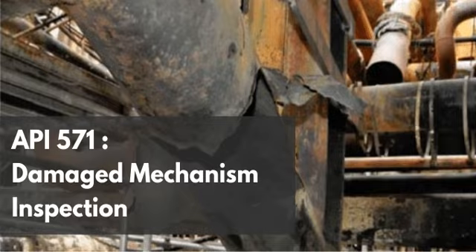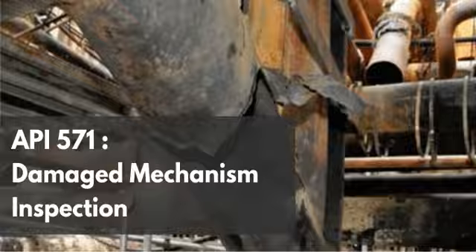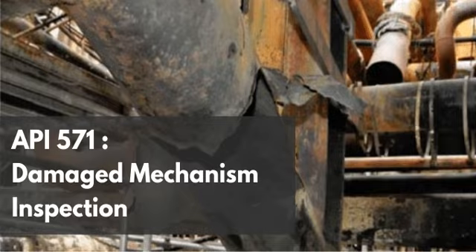If we connect this to the bigger picture, the temperature limit in an amine unit isn't just about the physical heat tolerance of the metal piping. Right, because the steel can handle way more heat than the process limit. Exactly. The carbon steel won't melt at these temperatures. The limit is entirely about the thermal breakdown threshold of the chemical amine solution itself. If you push the temperature too high, usually in an attempt to strip more gas out and increase unit efficiency, you are literally cooking your treatment chemical.